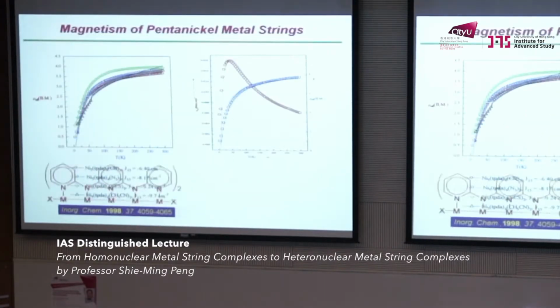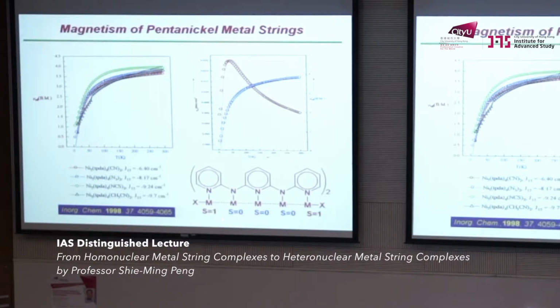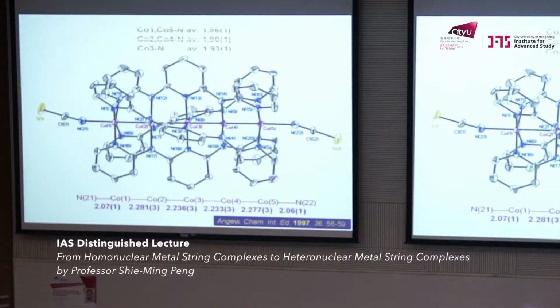Forget it. So the spin state is 1, 0, 0, 0, 1. So they are farther away, and the antiferromagnetic coupling becomes much weaker than in the previous trinickel one. If we move from nickel to cobalt, from d8 to d7, now you have a metal-metal bond. The cobalt complex has a distance that is shorter than the previous nickel distance, by about 0.1 angstrom.